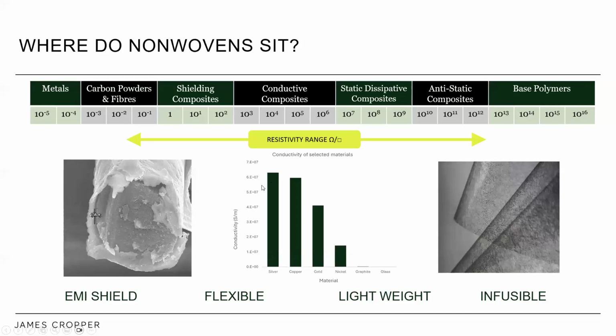So my name is Mark James, and I'm just going to briefly summarize some of the benefits of using our conductive nonwovens. On this slide, I've basically just shown at the top the range of resistivity of metals to base polymers, spanning nearly 21 orders of magnitude. The resistivity range covered by our nonwovens is highlighted by the double-headed yellow arrows. On the left would be our metal-coated carbon veils, and on the right would be our dielectric veils made of glass or polymers. And the central portion is covered by blending a fiber mix of our conductive and dielectric fibers. Even a small coating of the metal on the carbon fiber enhances the conductivity significantly. And on the next slide, I'll just cover that a little bit more.